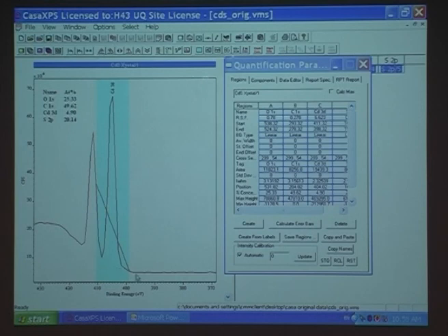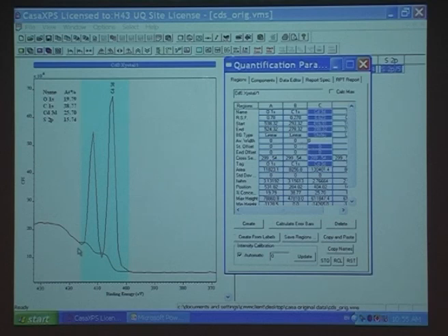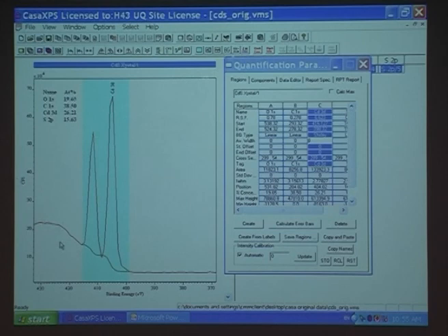I should be taking the area of both these peaks. So I'm going to move this up to here. And you can see the background's here, and then it's stepped up quite a bit. When you've got a big change in the background, it's a bit more preferable to use what they call a Shirley background. You've just got to type in S. It doesn't change it too much, but it's S. The Shirley background takes care of the fact that the background changed from the start of the peak to the end. Now, when the background's the same on each side, doesn't matter, Shirley and that are still linear. Shirley ends up linear. I use it for these ones where we've got the change in the...